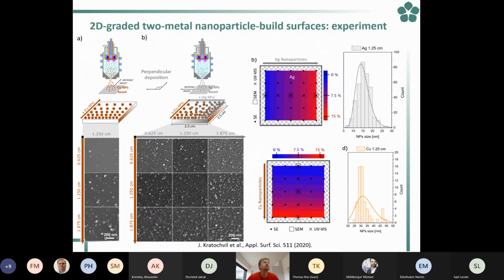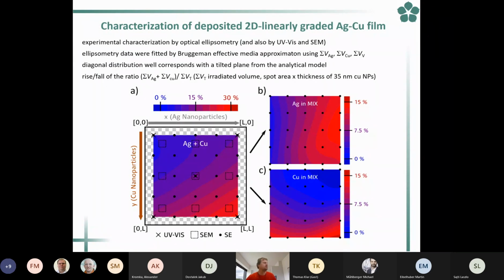species. But actually, today, I think it was in the talk of Jakub Dostálek, we saw quite a nice double peak SPR graph, which we try to do as well. For example, here, when we studied these two metal nanoparticle built surfaces. What we try to do is the preparation of the composite, which consists of two nanoparticles, for example, silver and copper, which we try to deposit in a really defined way. And here you can see that we were able to deposit some matrix or nanocomposite with the defined composition between the silver and the copper nanoparticles, which was quite interesting for us, because in each point